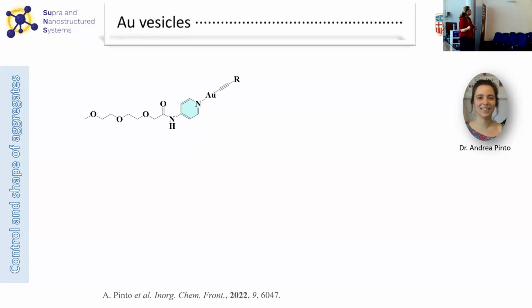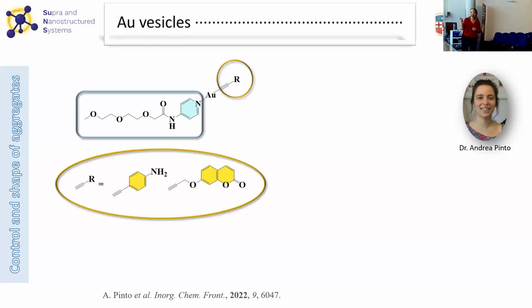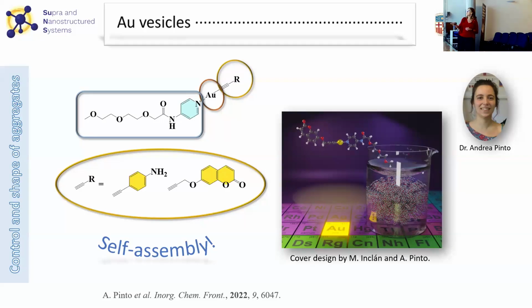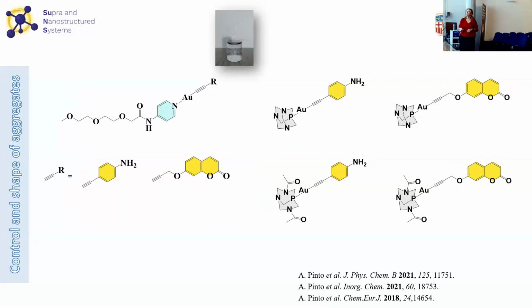So we decided to move to self-assembly, but with more rational control. And in this case, Andrea synthesized this compound containing this polyethylene glycol chain that is coordinated to the metal center through a pyridyl. And at the second coordination position, she introduced these chromophores that can be an ethinyl aniline or a propargyl coumarin. And we played with the self-assembly in order to construct complex structures like those presented here.